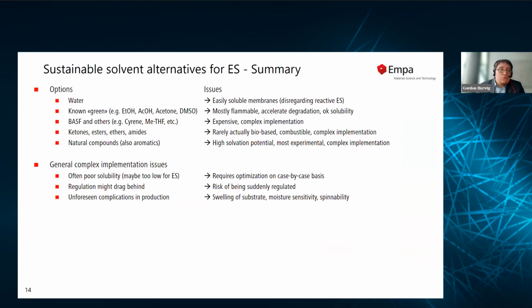Relatively simple. There are two options. Either you go with the very easy to use solvents, for example, as I mentioned before, PVDF-HFP as a relatively high quality polymer you can dissolve in DMF, but also in DMSO acetone mixtures. The acetone is a relatively small amount in there. You can also achieve similar stuff with ethyl acetate as a co-solvent. They increase the solubility a lot, but they are small enough in amounts that they are not a risk of getting into combustible limits. So they're still safe to use, but you have to invest something.